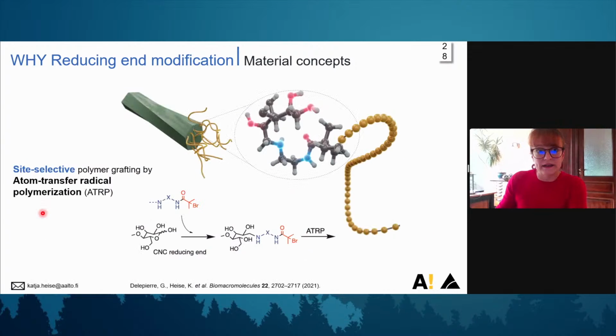Okay, what we did, and I just want to very, very briefly show this with Quen, is polymer grafting at the reducing end groups. It's a work from last year. So we use atom transfer radical polymerization because it's very controllable. And for that, the key step is that we actually really selectively attach a polymerization initiator to the reducing end groups. We do this with reductive amination, and then we graft polymer chains from this generated macro initiator.